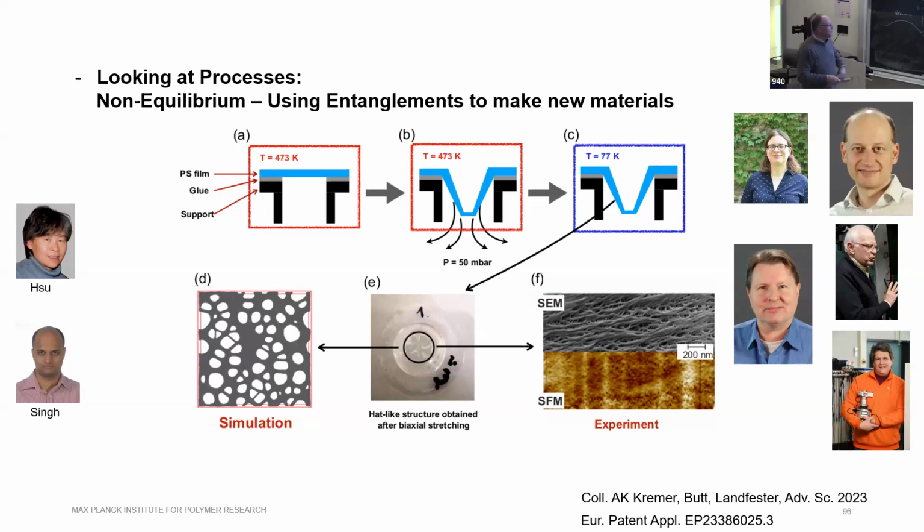And now you can take the diameter here. So we know that if we map the tube diameter of polystyrene onto our model system, then the tube diameter of the model system is 5 sigma Lennard-Jones units. Polystyrene is 5 nanometers. So 1 sigma corresponds to 1 nanometer. And that means we have here about 30 to 50 sigma. And here, when you take the scale bar, we have about 50 plus minus 20 nanometers. So that is almost quantitative.